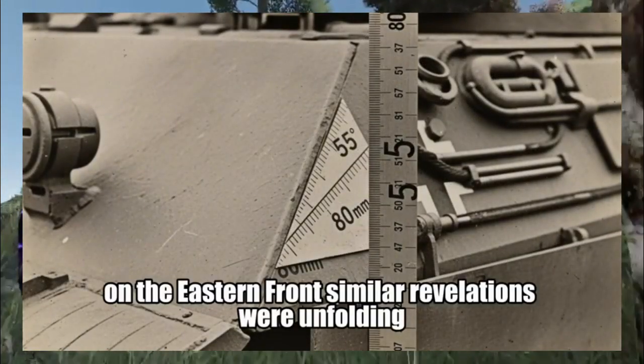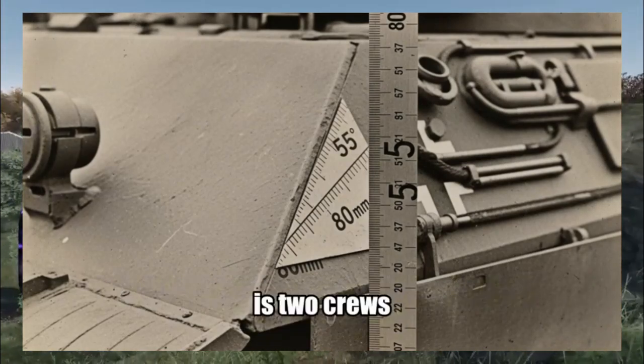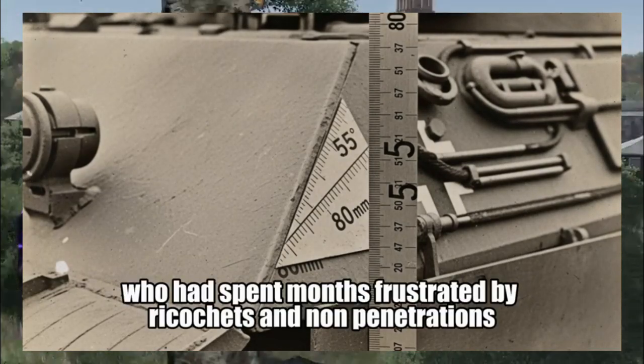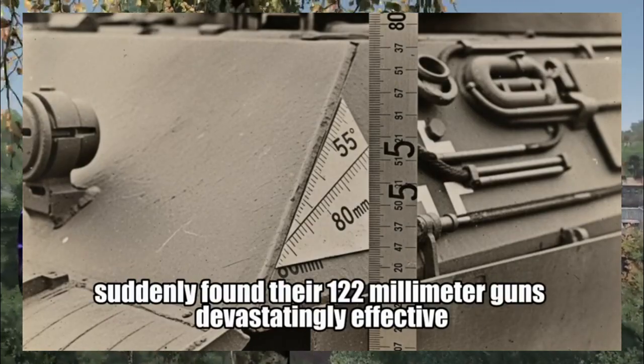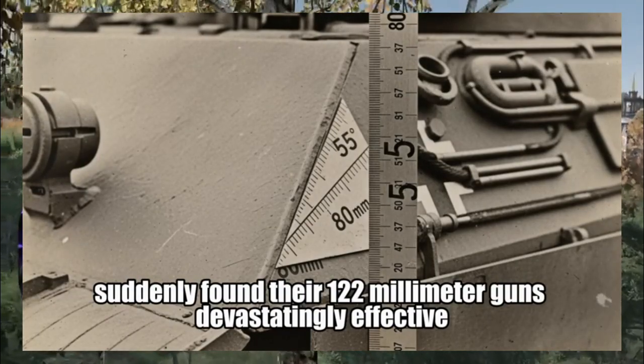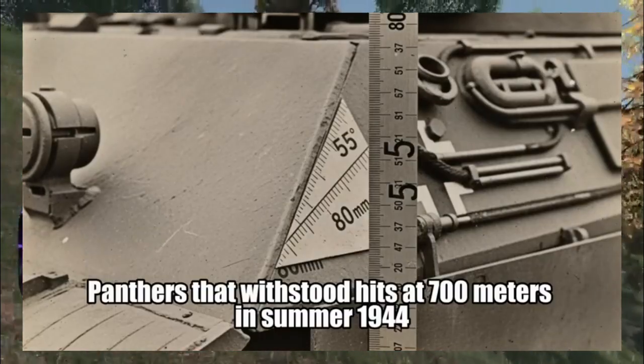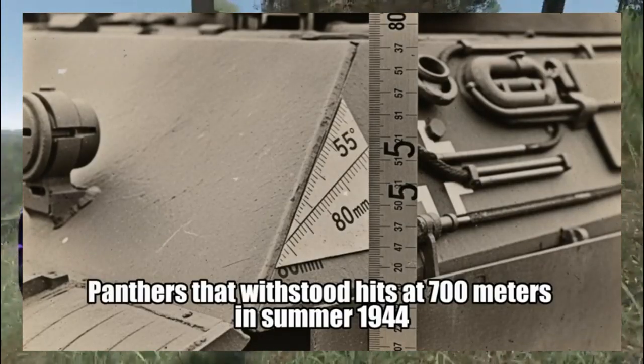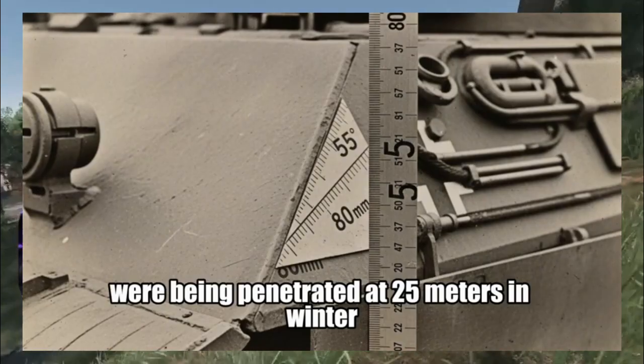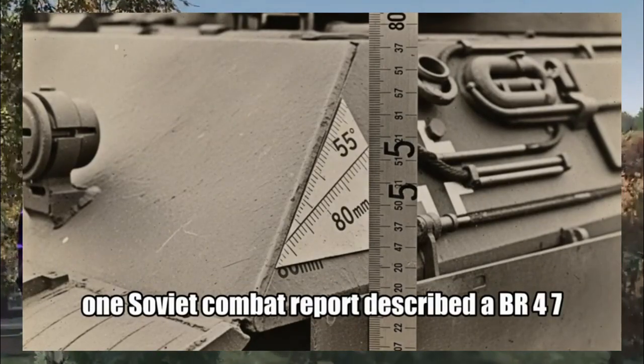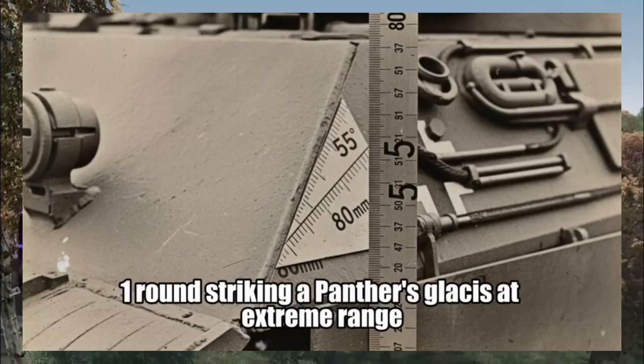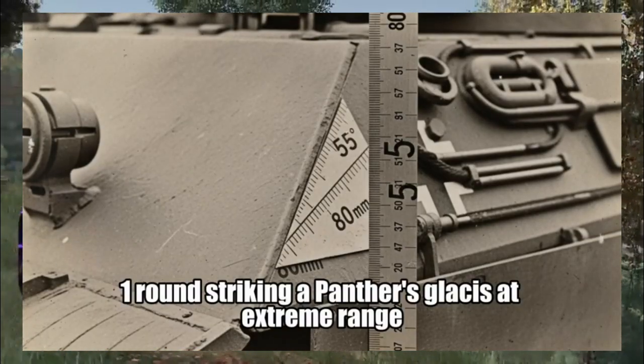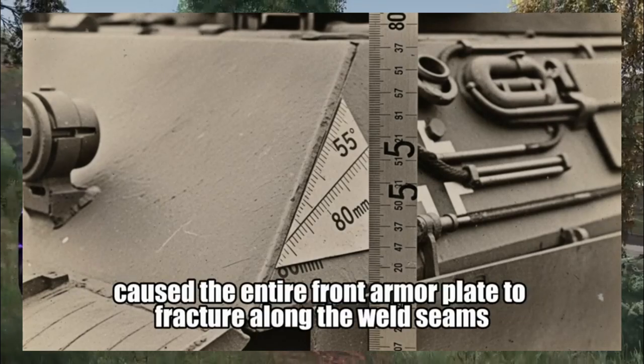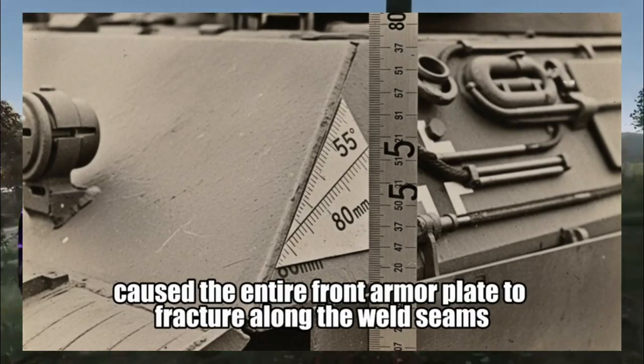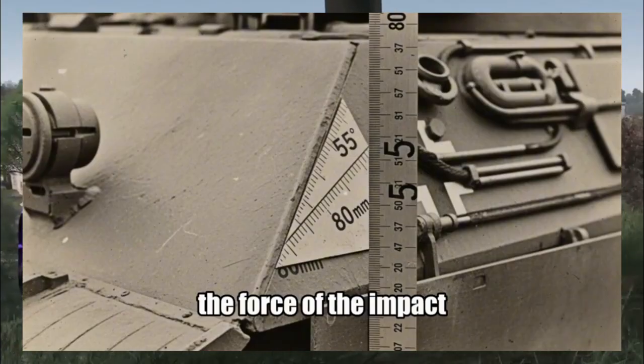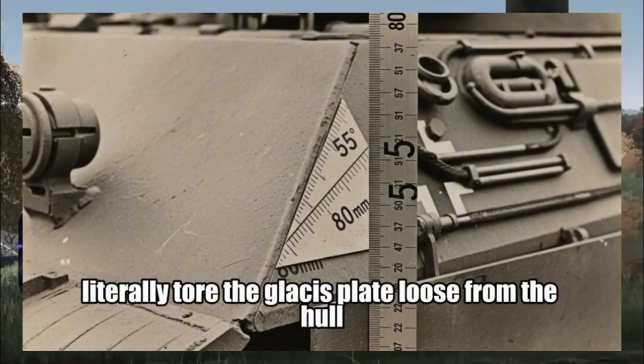On the Eastern Front, similar revelations were unfolding. IS-2 crews, who had spent months frustrated by ricochets and non-penetrations, suddenly found their 122mm guns devastatingly effective. Panthers that withstood hits at 700 meters in summer 1944 were being penetrated at 2,500 meters in winter. One Soviet combat report described a BR-471 round striking a Panther's glacis at extreme range. Instead of simply penetrating, the shell caused the entire front armor plate to fracture along the weld seams. The force of the impact literally tore the glacis plate loose from the hull.